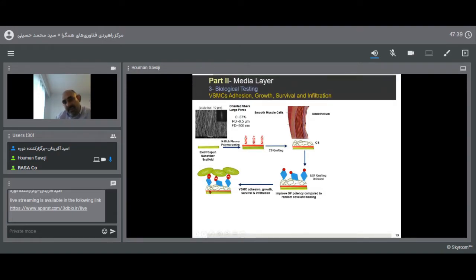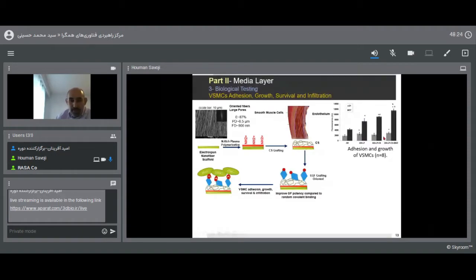and scaffold bioactivity. And then we studied the vascular smooth muscle cells and their communication with the scaffold. As you can see, the bioactivity or the growth has been promoted on the surface with the growth factor immobilized scaffold compared to the control sample, and this was significant across the different layers of the scaffold: you have only primary amine, you have only the chondroitin sulfate, and you have the growth factor on top of that. So the adhesion really didn't change, but the growth has changed a lot.